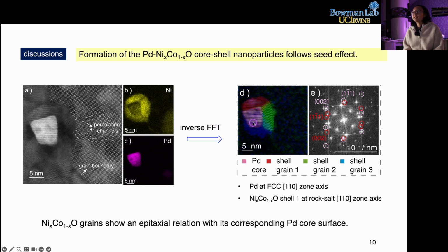So we use the inverse FFT to track the location of each shell grain by using their FFT patterns, identify the FFT pattern of each shell grain and color it in the inverse FFT image. Then we compare the shell grains' FFT with the palladium core's FFT. We found the nickel cobalt oxide grains show epitaxial growth with the corresponding palladium core surface. That means each shell grain will grow epitaxially on the corresponding palladium facet.